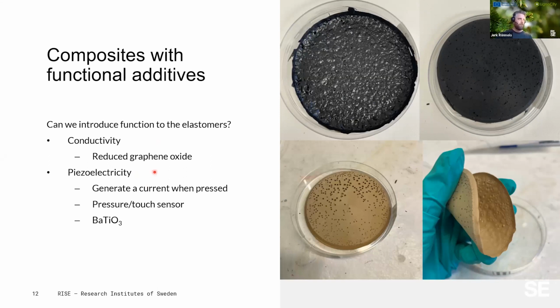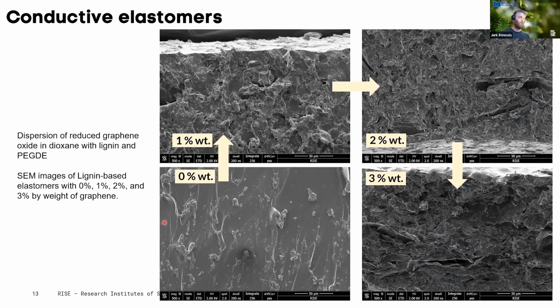So to make it conductive, we experimented with introducing reduced graphene oxide, in essence, graphene. And for the piezoelectricity, we introduced barium titanate, which is a good material for that. And how did that go? Well, it was possible to disperse reduced graphene oxide in dioxane together with the lignin and the PEGD, the crosslinker. So we blended it all together. Dispersing graphene is quite tricky. It requires a good system, but actually it worked well in this. And we believe that the lignin particles are acting somewhat like a surfactant for the graphene itself. So it helps it blend in.